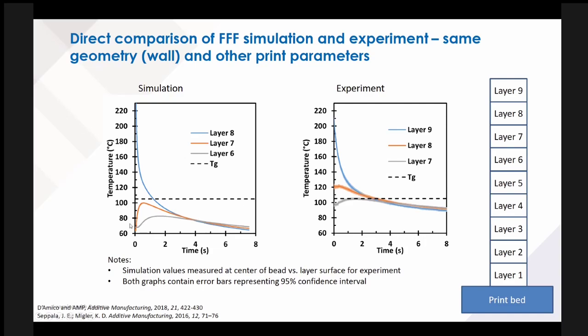We see in our simulations, and also in the experiments, that there is a little bit of a lag for the lower layers between when they start to heat up and when the initial deposition occurs. That's just because it takes a little bit of time for energy to conduct through the layers. We do see our simulations are overestimating the increase in temperature upon deposition of the next layer, and we're also overestimating some of the cooling, which is related. We think this is probably due to some of the simplifications we've made in the models, but again we end up having fairly good agreement at this level.